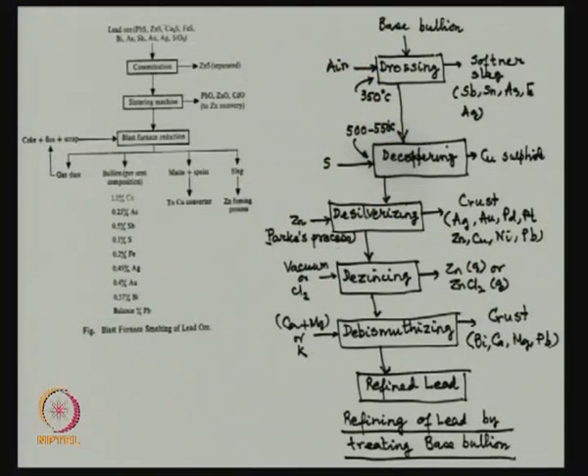It is necessary because the concentrate coming out of flotation is very fine. If we just roast it as it is, whatever you get will be very fine — we do not want that. So, the roasting is done in a sintering machine, the Dwight Lloyd sintering machine, which is a continuous operation. From the concentrate, we get particulate matter sinters which are suitable for going into the blast furnace.